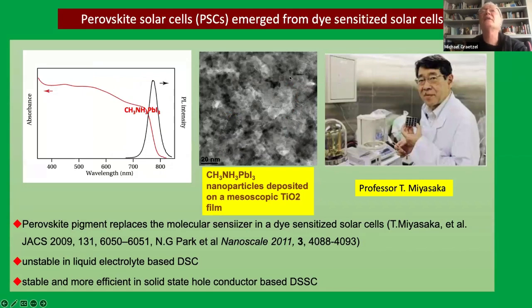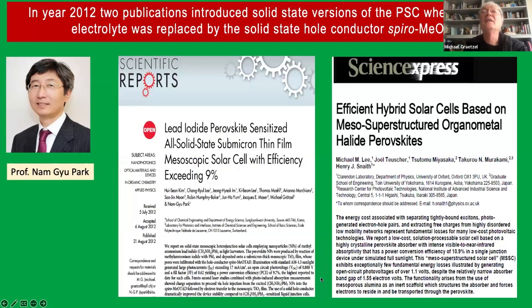And so this technology started with Miyasaka's work on DSC that used nanoparticles of methylammonium lead iodide, the perovskite, as sensitizer. However, these were unstable in the liquid electrolyte, because these are ionic crystals that dissolve in polar solvents, and so the switch to the solid-state hole conductor was key to the present development, and so two papers appeared.